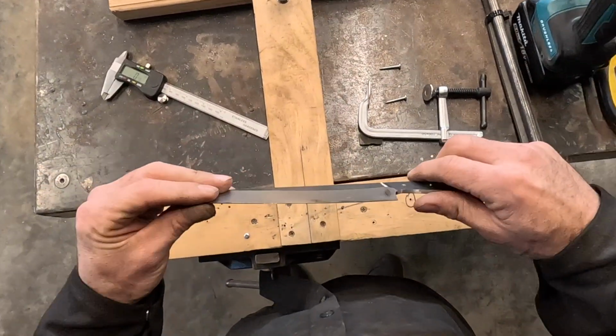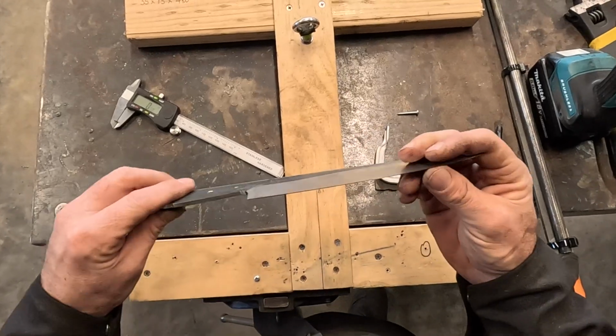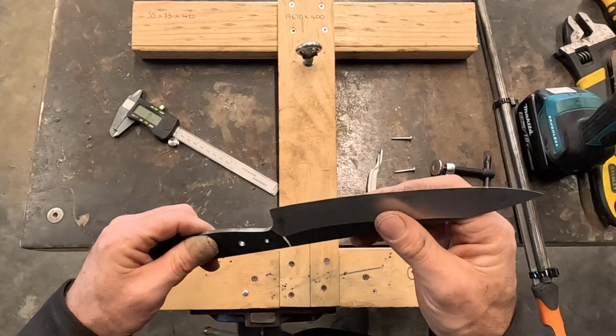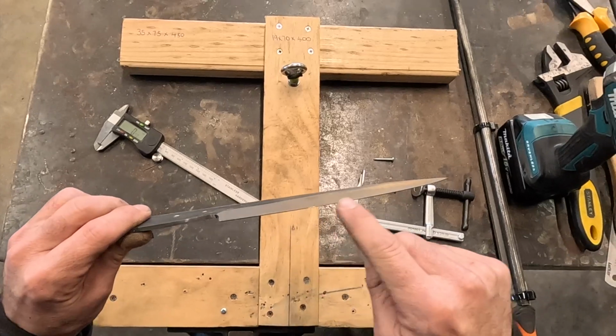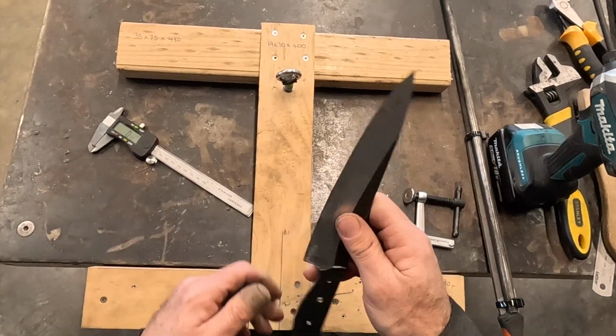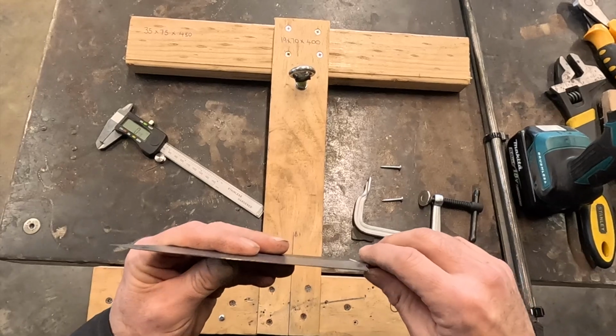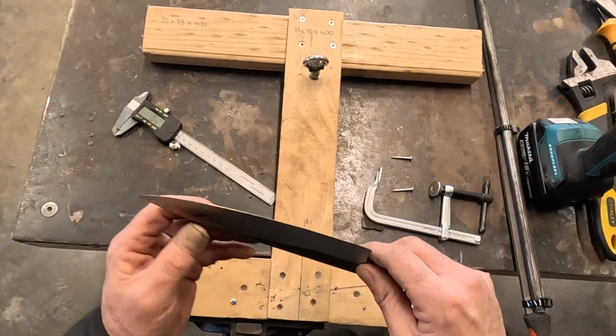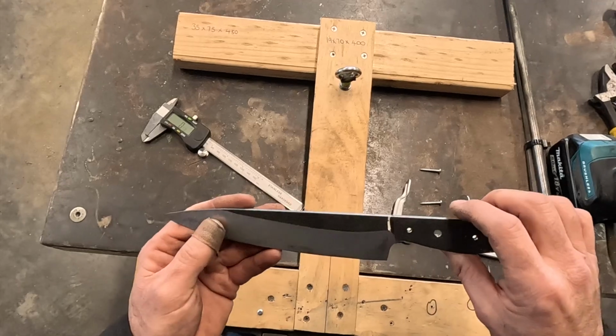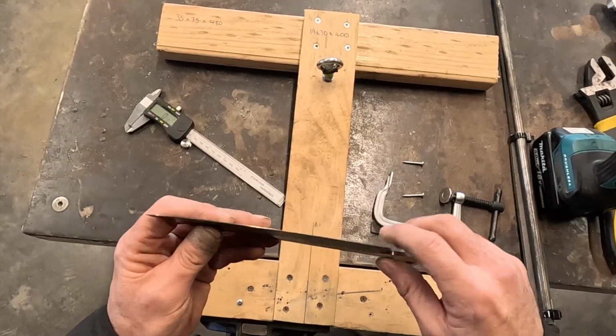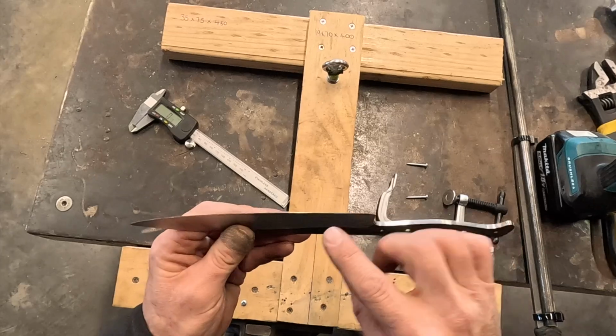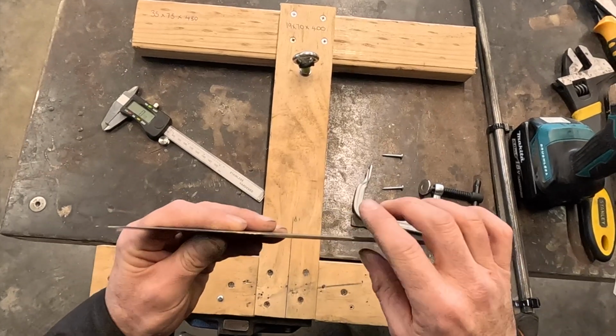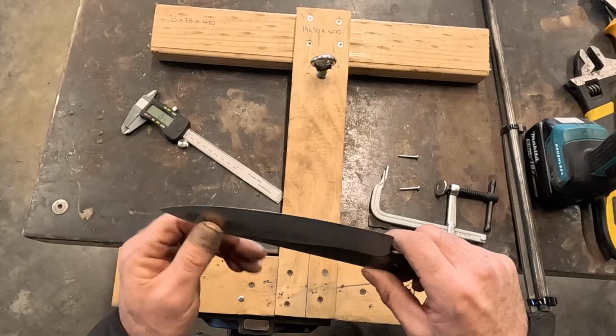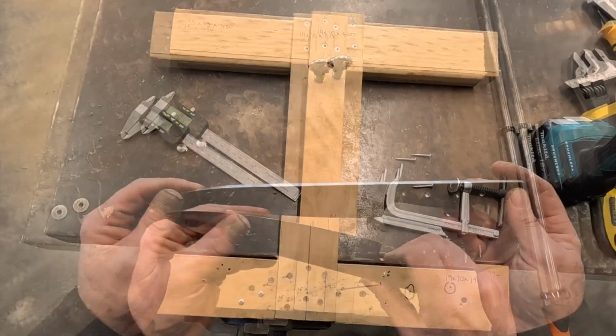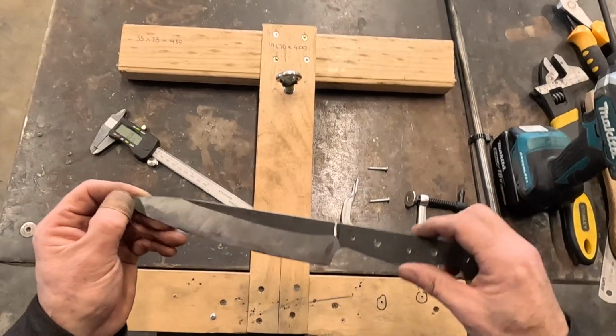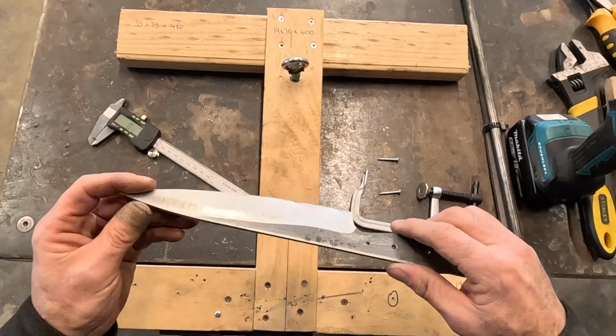So around that 0.7. The reason that we want 0.7 is because it's much thinner and the blade will ribbon under the heat of the forge, and any thicker and it takes too much to sharpen. If you get to this stage and it's 0.8 in one section and 0.6 in another, and you're a bit worried you don't want to file anymore, you can pre-sharpen in the sharpening machine before you heat treat, and that will save you some time at that next stage.